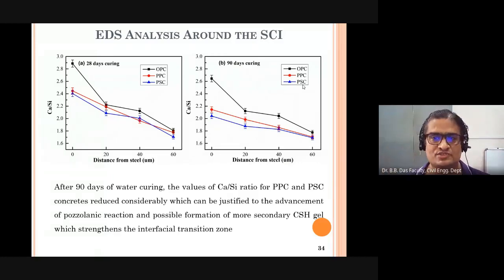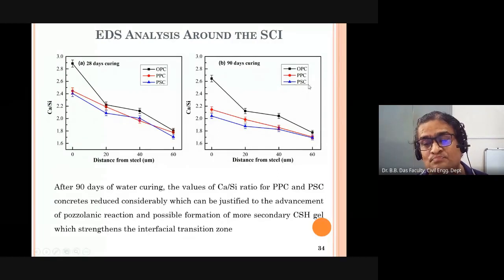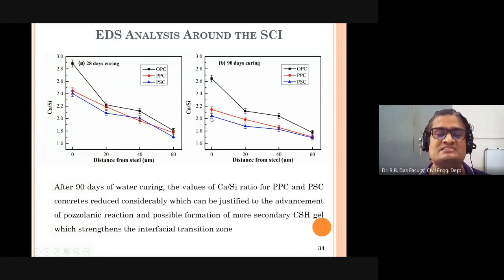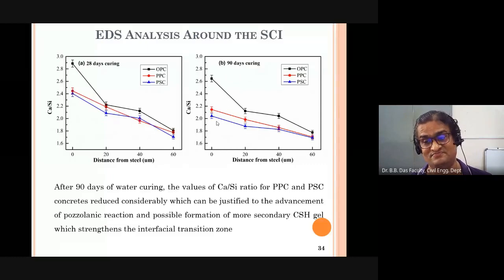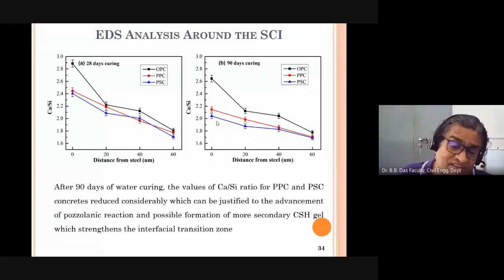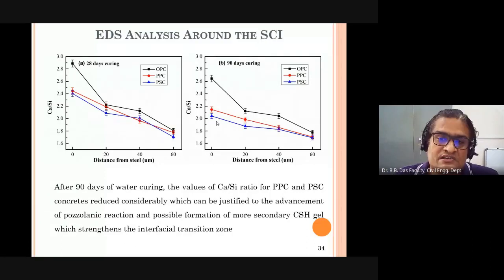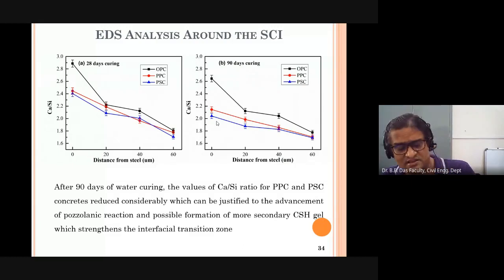Now, this is a universal thing. When I go for the PSC, Portland slag cement, compare: this is my OPC, this is my PPC, and this is my PSC. PSC has a much lower Ca by Si ratio, meaning more formation of calcium silicate hydrate gel as compared to PPC and OPC. OPC is much more than PPC and PSC, but PSC is still better than the PPC. That is why researchers recommend PSC in most important constructions. So this is what we learned from this topic.